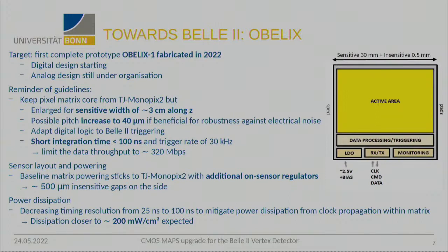We want to keep the pixel matrix from TJ Monopix 2, but instead of using 2 by 2 centimeters squared, we want 3 centimeters in one direction and 2 centimeters in the other. Maybe we increase the pitch to 40 micrometers, currently it's 33 micrometers, to have more robustness against noise, and adapt some logic for Belle II triggering. We can likely come along with 100 nanosecond integration time, because our level 1 trigger rate is only about 30 kilohertz, and we want to limit the data throughput rate to something reasonable.